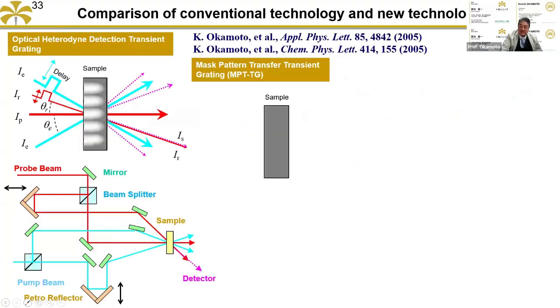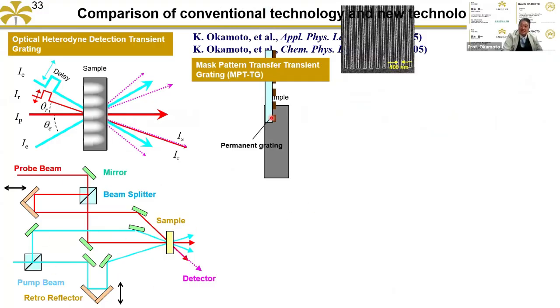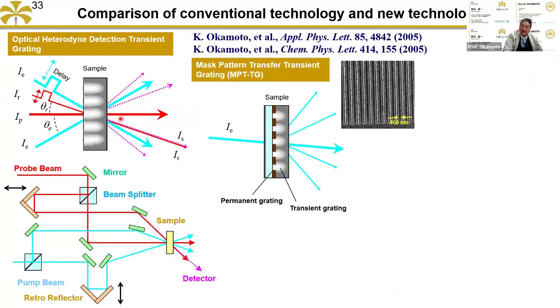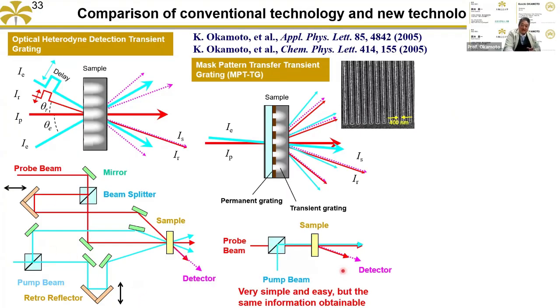But usually the alignment is very difficult. The three beams must be coherent, and to enhance the light, the three beams must also be coherent. That's very complicated. But using the fabricated metal nanograting, with just one beam you can obtain the spatial distribution of the light. That's why it's easy. Just two beams are good enough to form this formation, so the optical alignment becomes very simple.